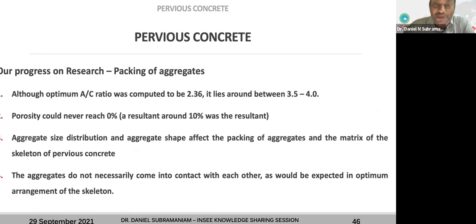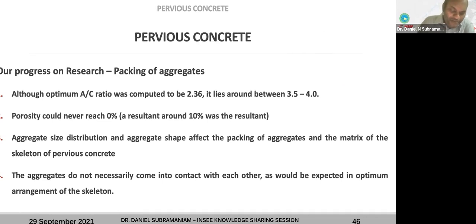And aggregate size distribution and aggregate shape affect the packing of aggregates and the matrix of the skeleton of pervious concrete. So the aggregates do not necessarily come into contact with each other. Now, what our exact concept would be like 2 aggregates, when you give compaction, they will move with each other and they will come in contact with each other. But in pervious concrete, in actual situation, it doesn't happen. So they will have a resultant thickness of binder in between them. So because of that, we will not be able to get to that 2.36 optimum AC ratio.